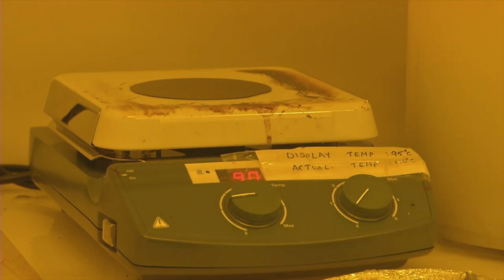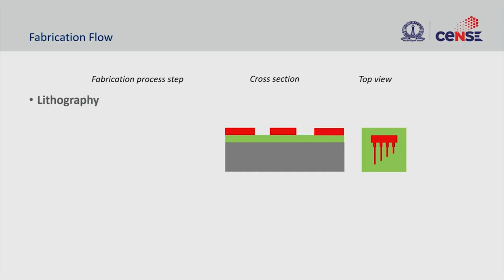What we are trying to do here is to remove all the moisture or water that was present on the wafer. So we are done with the lithography now. As we saw from the top down images, we had the structure where we had silicon nitride, and this is your photoresist that is sitting on top of the wafer. Now we have to transfer this photoresist pattern into silicon nitride, okay.